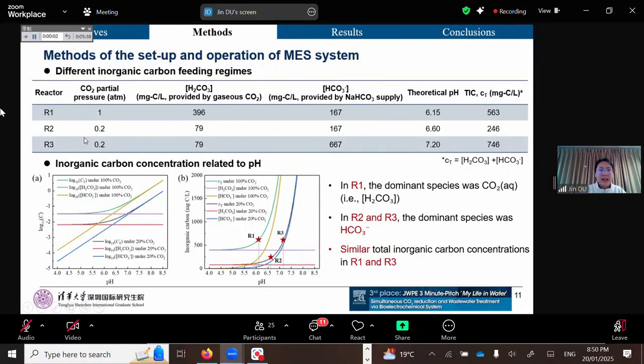As you can see on my slide, we operated 3 reactors in parallel. One was supplied with pure CO2 gas and buffered with baking soda. The main inorganic carbon source was gaseous CO2 for R1, while R2 was supplied with 20% CO2 gas and buffered with the same amount of baking soda as R1. The main inorganic carbon source for R2 is the dissolved bicarbonate. R3 was supplied with 20% CO2 gas, but with an additional dosage of baking soda to match R1's total inorganic carbon concentration.